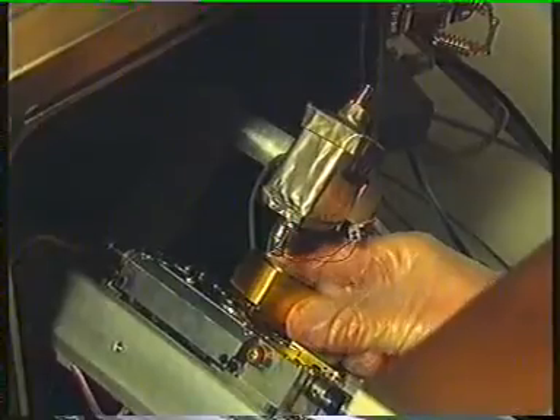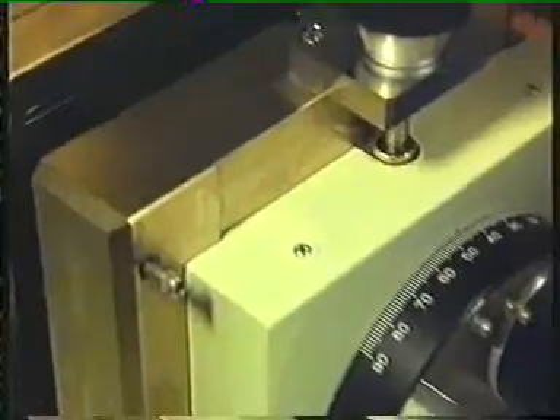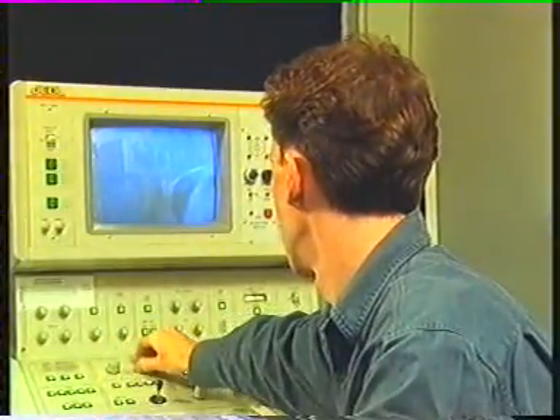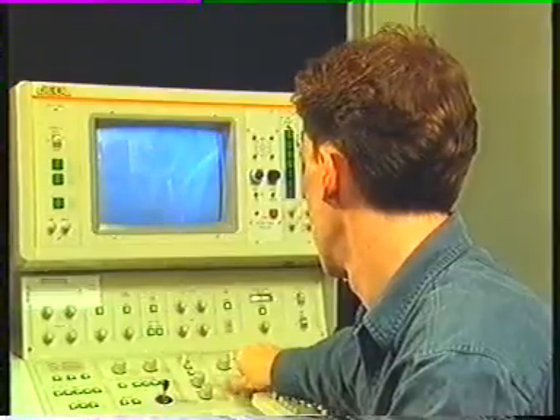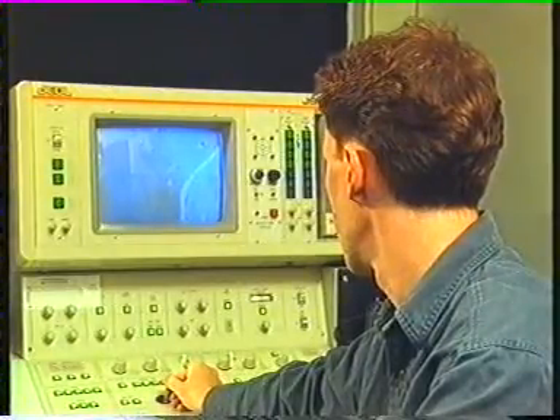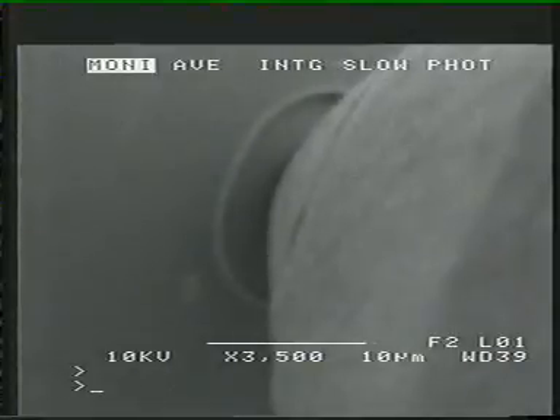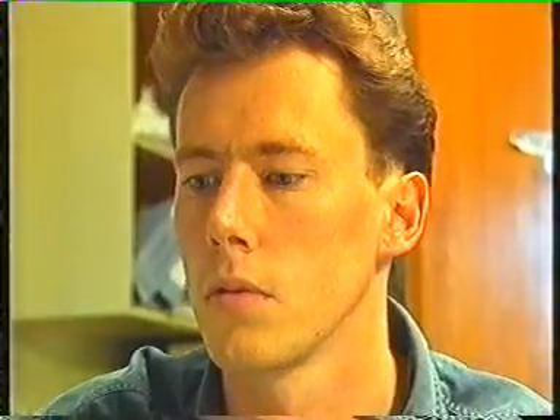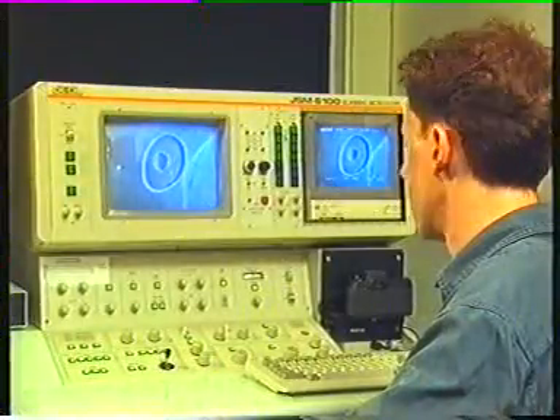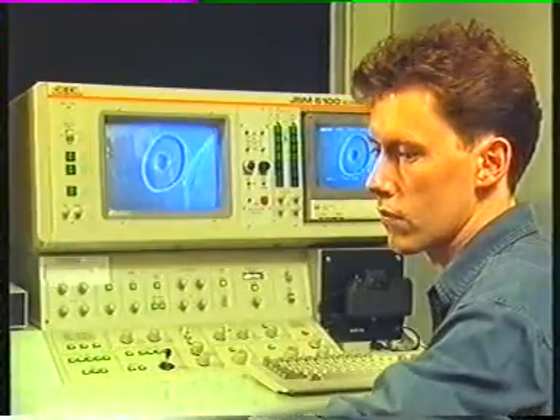Much of the work being done by scientists at the University of Warwick centres around the interface between fibre and matrix. In this experiment, a diamond tip is being used to push the fibres into the matrix in order to see how they fail. This one is brittle. See how it gives way suddenly. This particular interface would not be ideal for use inside an aeroplane. The very imaging technique being used in this experiment is new. Work on high temperature materials is stretching the boundaries of science as well as engineering.